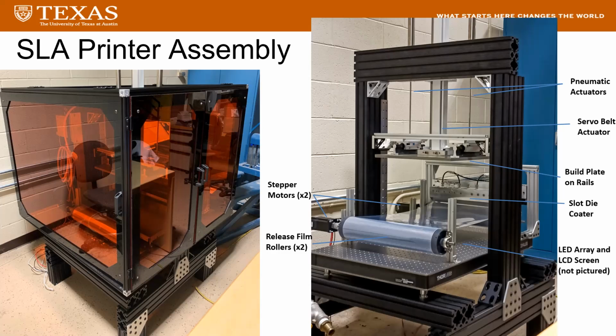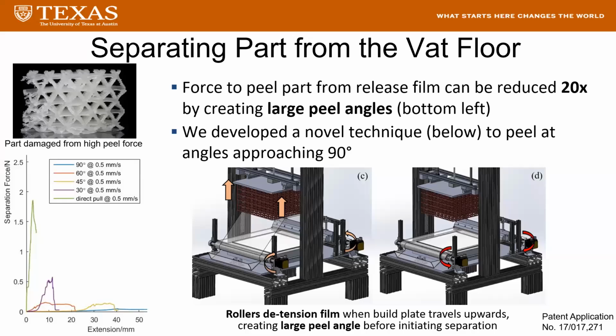So rather, we are coating 500 micron layers of resin on the release film, each layer, using a slot die coater and a progressive cavity pump. And you can see on the left, the entire printer is enclosed in a UV-proof enclosure. So the release film onto which the resin is coated is wound between two rollers that can control the tension in the film. To coat each layer of resin, the film translates to the left while the slot die coater is extruding a line of paste, spreading it into a film of about 500 microns.